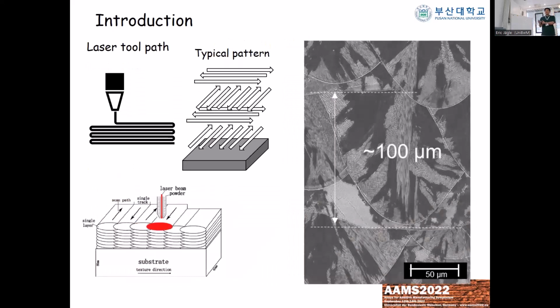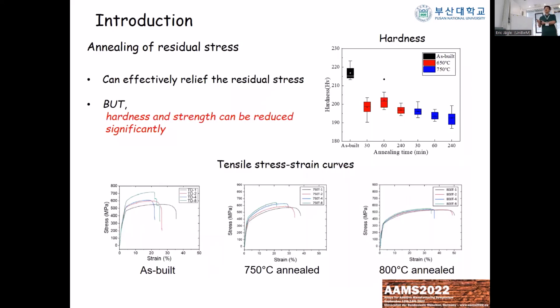There are many studies that try to control the residual stress by optimizing the laser pattern or by adjusting printing parameters such as laser power and so on. But this is basically unavoidable because we are depositing hot material on the cold substrate or the previously deposited layer, and this shrinks. So there's always strain mismatch, and we have some amount of residual stress. Maybe we can reduce it, but we cannot completely eliminate it during the process.